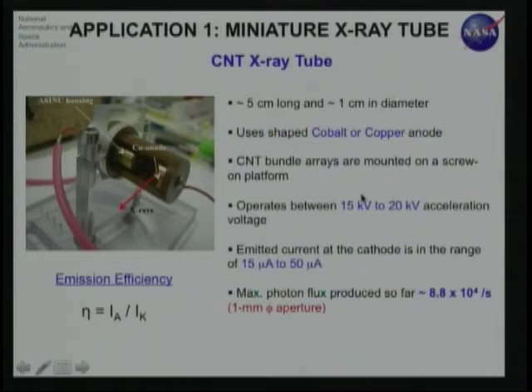As I mentioned, it operates at a low acceleration voltage, 15 to 20 kilovolts. We have a certain current that is emitted, and then you produce about 10 to the power of 5 photons per second, which is a reasonable photon flux for measurement purposes.